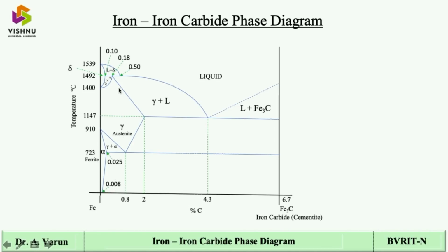What we can notice here is delta having a maximum of 0.1% of carbon, gamma 2% of carbon, and alpha 0.025% of carbon. When carbon is dissolved in gamma iron, in short, we call that austenite. And when carbon is dissolved in alpha iron, we call that ferrite. We'll also come back to that during the invariant reactions.